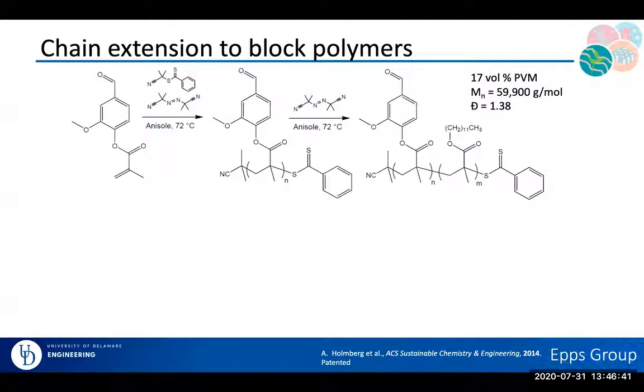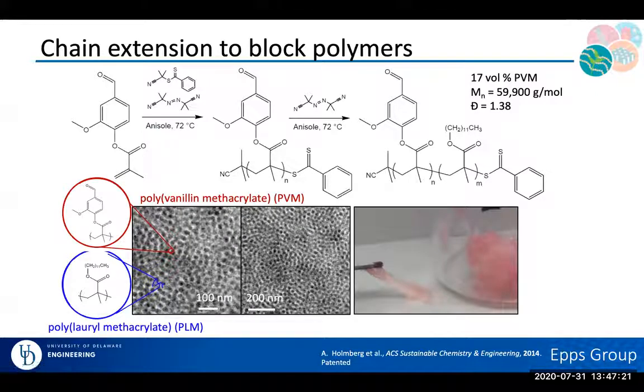So now that's quite nice, but one of the key things that I mentioned is, can we actually then take these materials and make nanostructured block copolymers? And so the answer is yes. We actually, in this case, used a RAFT polymerization, so a controlled radical or pseudo-living radical type polymerization. We took vanillin as our lignin-based component, methacrylated that, and then we actually made a block copolymer of that with lauryl methacrylate, so basically something I could obtain from used cooking oil. Got a relatively well-defined polymer, and then we can image that polymer and analyze it.